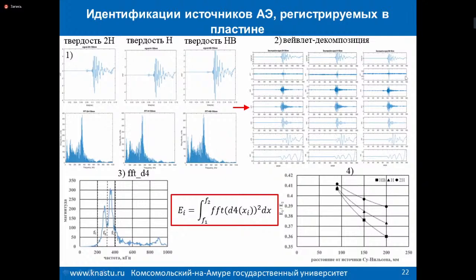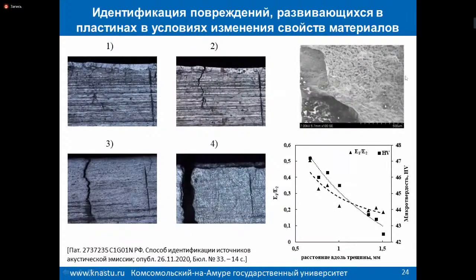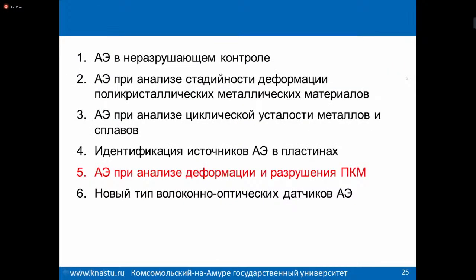And there is a relation of two energies which were obtained by low frequency component and high frequency component of signals of the fourth stage. It was about 300, 400 kilohertz. There are shown the pictures where the crack was going closer and closer to its destruction.